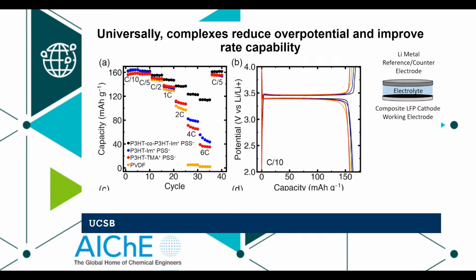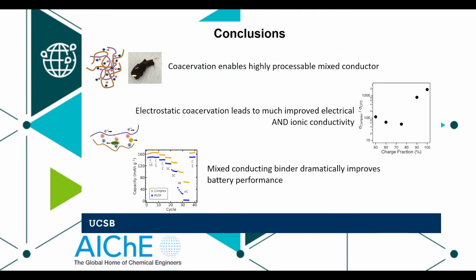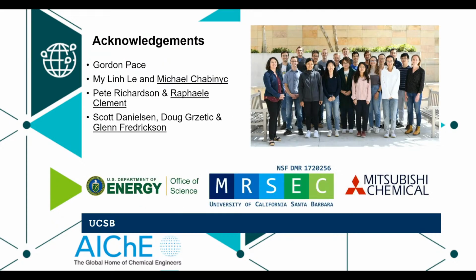That black data is the best one we've made so far, where it has really impressive capacity at very, very high charge and discharge rates. And you're seeing that we're running at very minimal overpotentials and maintaining that rate capability. Okay, so what I've tried to show you is that you can use these biological concepts like coacervation to make really highly processable battery components. The coacervation leads to improved electrical and ionic conductivity for reasons that make physical sense. And together, that mixed conducting binder dramatically improves battery performance, particularly in the next generation electrodes that we're going to be using in the near future.